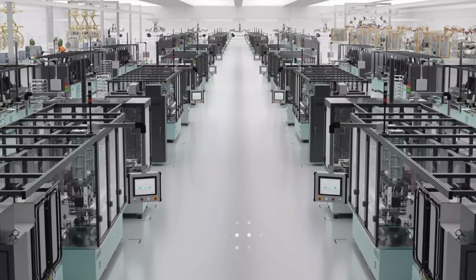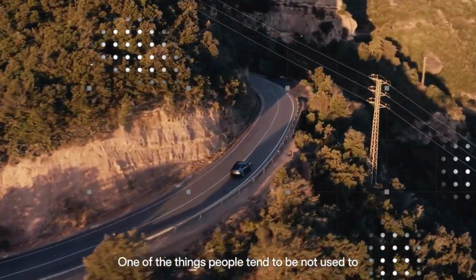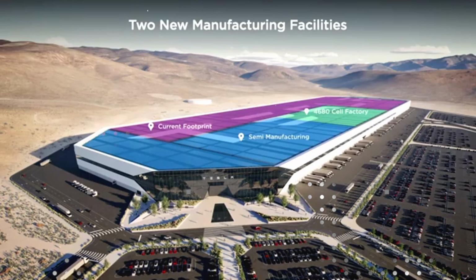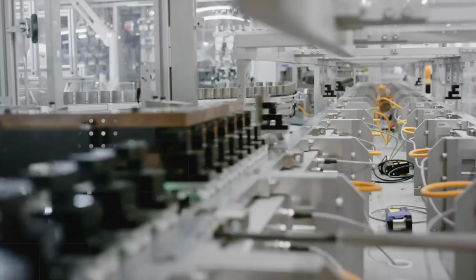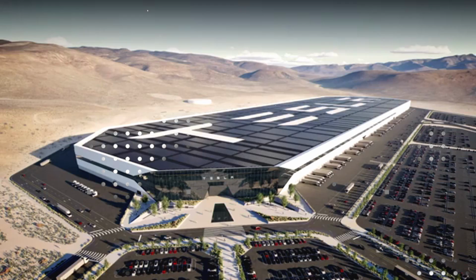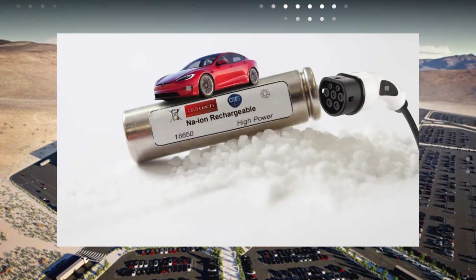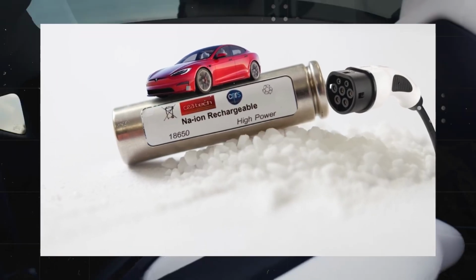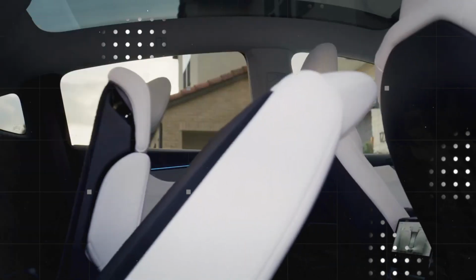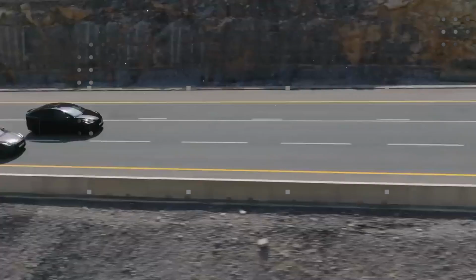The peak temperature in a faulty cell didn't exceed 88 degrees Celsius, and in less than 90 seconds, it had already dropped below 60 degrees. No neighboring cells ignited. In other words, the battery not only survived the attack, but also managed to prevent any thermal propagation. Tesla isn't banking on luck or quick human reactions. The system itself takes action before danger has time to arise.